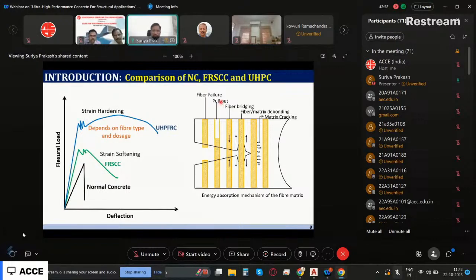In fact, through the pull out mechanism only, a lot of this energy absorption in the cracking process is achieved. Then finally, if the anchorage is very good, when the crack width is becoming more, the fiber can actually fracture. This is what we call fiber fracture or fiber failure. Fiber can also completely pull out. It depends upon multiple factors. So these are all some of the challenges. This is the way the energy absorption mechanism due to fiber reinforced concrete arresting the crack happens.